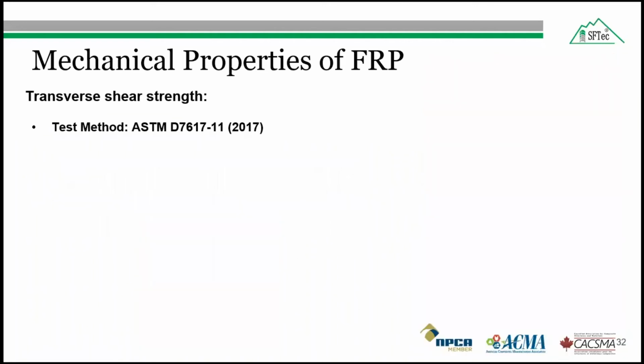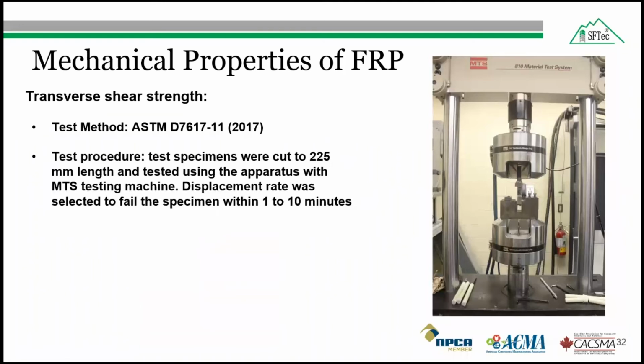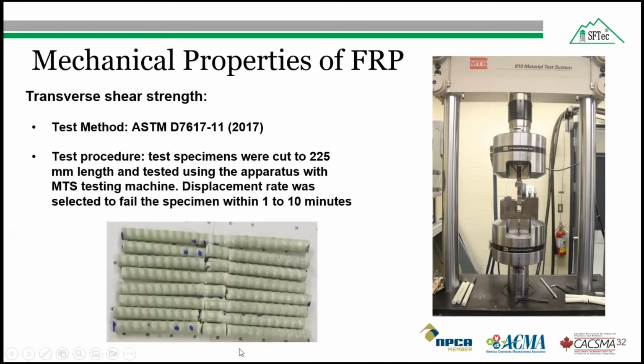For each production lot, we are going to test 8 samples. And the length of each specimen, irrespective of the bar size, was 225 millimeter or 9 inches. And the specimen was centered within the shear apparatus, resting against the bar seats and lower blades, and then the upper plate was placed onto the bar and the apparatus centered in the MTS universal testing machine. So the displacement rate was selected so as to produce failure within 1 to 10 minutes, and force was applied uniformly without subjecting the specimen to impact. This figure shows the failure of these bars in transverse shear.